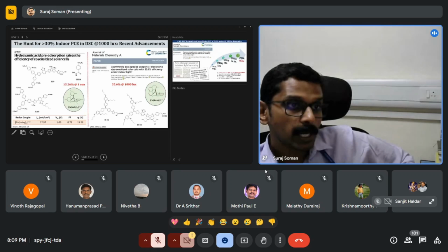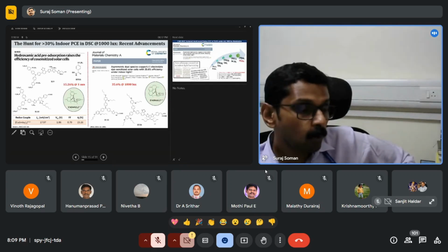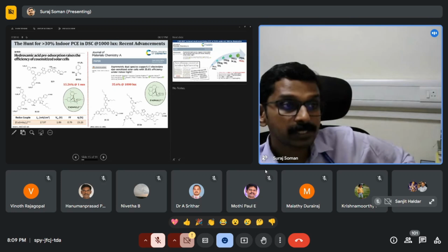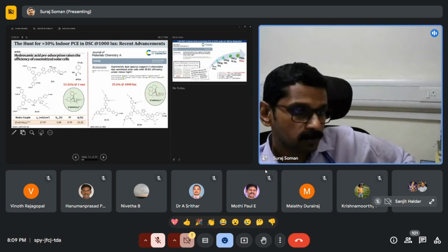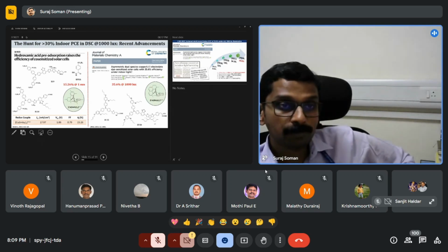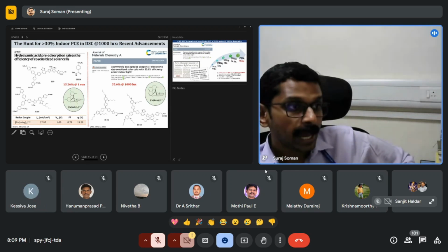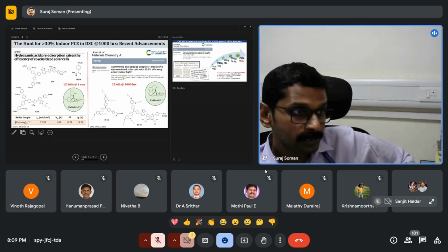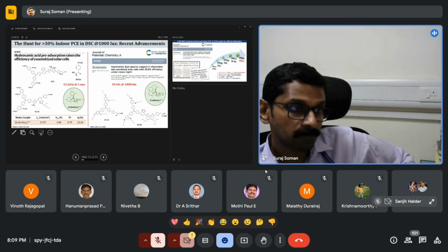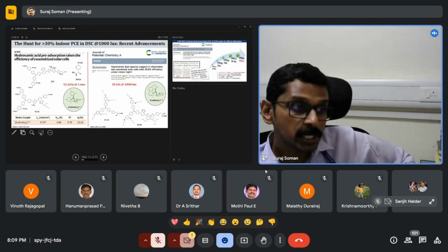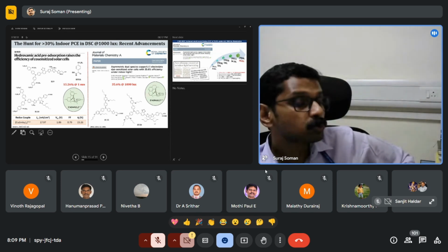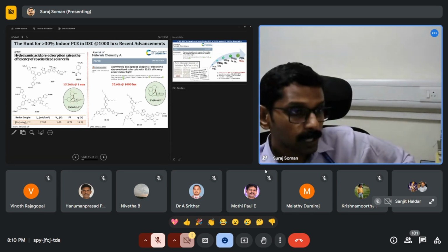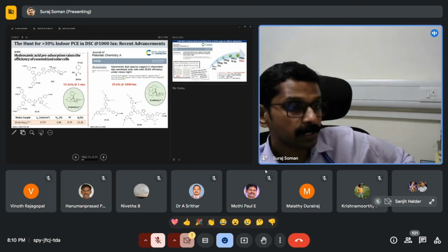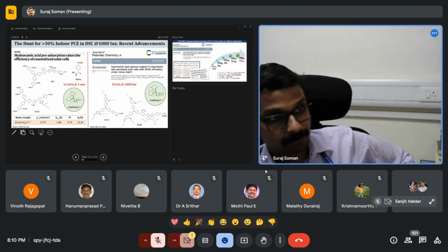One thing that you can observe in all these systems is that they all have the donor unit, which is triphenylamine. It has certain relevance when it comes to the dye-sensitized solar cell. Triphenylamine being a kind of starburst system, the branches attached to the triphenylamine molecule and the orientation of the molecule prevent the spatial approach of the hole, which is present in the electrolyte, coming close to your semiconductor. That is the reason why triphenylamines are used quite a lot in this kind of system.